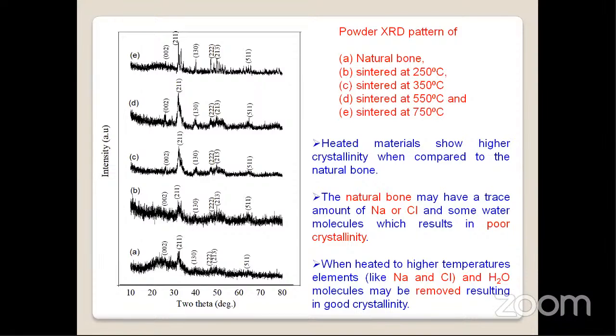By this, one can understand that heat treatment plays a major role in determining the crystalline stage. That means one can understand whether the material is getting a different structure or not. Up to 750 degrees centigrade, its structure remains the same. All the peaks are at their own positions, there is no change in peak position. They remain the same, though there may be some nano strain. When the temperature goes beyond 750 degrees centigrade, its structure changes.